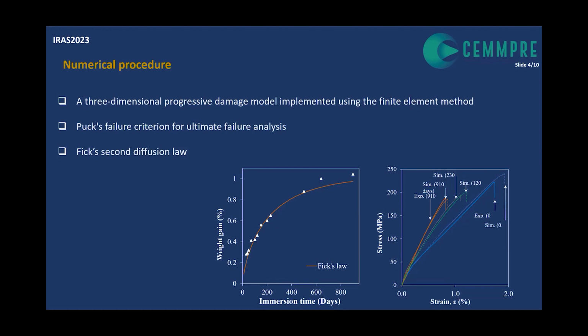Here on the graph on the left, we have some measurements of the weight gain and the implementation of Fick's law, and on the right, we have the stress-strain curve simulated numerically and obtained experimentally. The results of the simulations were good, and the immersion in seawater induced a significant reduction in the ultimate tensile strength, as well as a reduction in the ductility of the composite material.